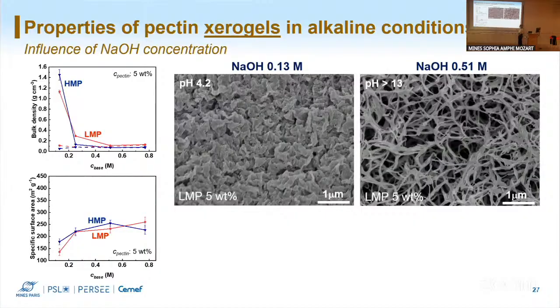I would also certainly suggest, probably not you, but to try the drying conditions themselves, because for silica, it's very sensitive to gas pressure, temperatures, solvent composition, so there's a lot of room with a given structure, just by changing the drying conditions, to optimize and push that boundary.